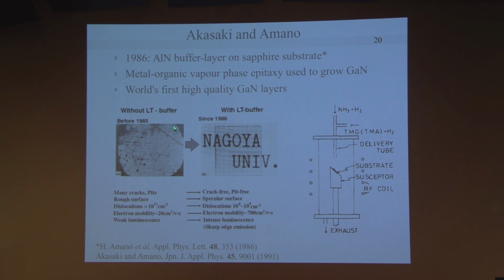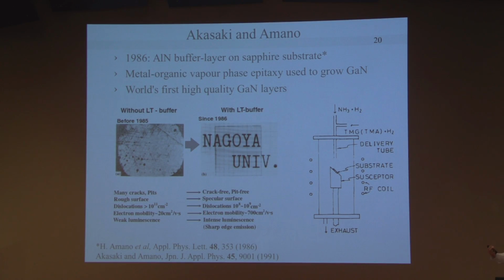And there's a picture here. This is a crystal grown without this buffer layer. You can see the dislocations and cracks in this film, and it has a poor mobility and very weak luminescence. And of course the gallium nitride layer itself will be transparent. There's a high band gap. That is what you see in this picture. You don't see it. The fact that you don't see the crystal means that it is high quality and nicely crystalline. And this has a much better luminescence and electroluminescence and electron mobility.